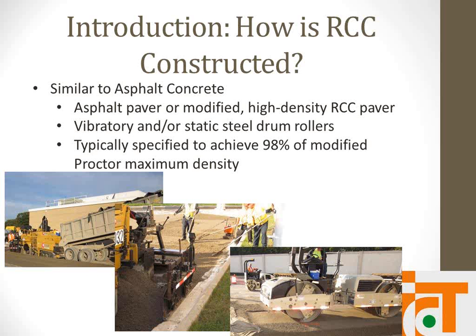And then how is it constructed? Basically the same as asphalt. It's brought from the mixed plant in dump trucks or even just typical concrete trucks and placed into a paver, and then the paver can either just be a typical asphalt paver, or if the contractor is experienced with RCC, they probably have a modified high-density paver with a screed bar at the end that will get densities of like 94 or 95% coming right out the back.